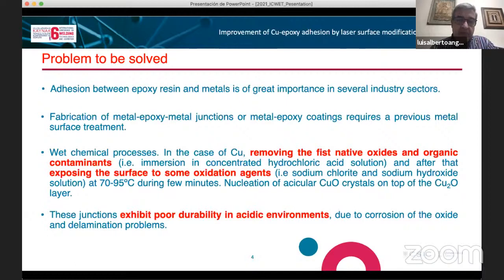And in principle, sodium chlorite or sodium hydroxide solutions at temperatures between 70 and 95 degrees during 3 to 5 minutes. And it creates a nucleation of acicular CuO crystals on top of the Cu2O layer. The problem with this junction is that they exhibit poor durability in acid environments due to the corrosion of the oxide and the delamination problems.